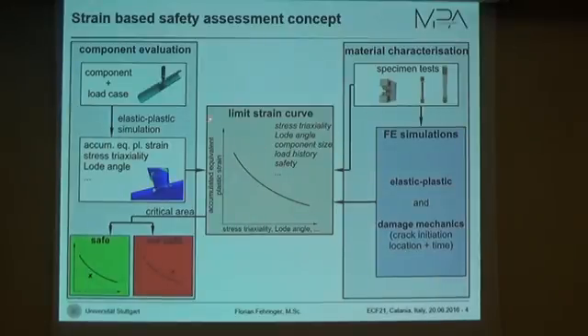When we have our limit strain curve and we want to evaluate a component, we take that component and an assumed load case and just have to do an elastic plastic simulation. We take our plastic strain and our influence parameters out of the elastic plastic simulation and look into our limit strain curve, and if we are below the limit strain curve, the load case in the component should be safe. If we are above, then it's not a safe loading case.